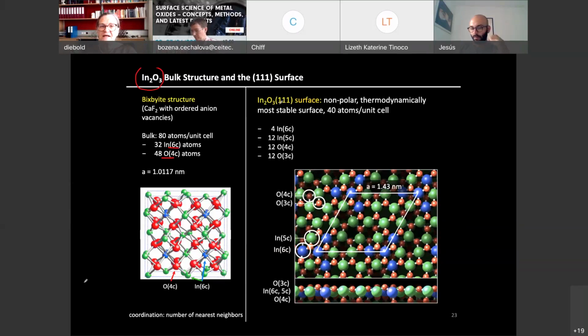And then if one cuts it in the 1, 1, 1 direction, this is how the surface looks from the side. You have indium and oxygen. Unfortunately, this is drawn wrong. The indium is actually big and the oxygen is small. It should be the other way around, as I told you. But you have layers of indium, oxygen, and indium.